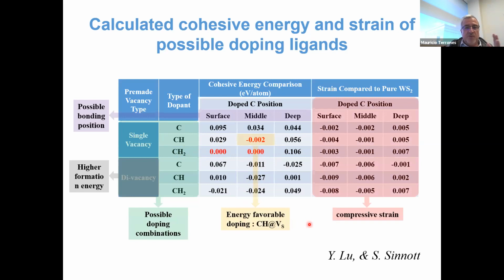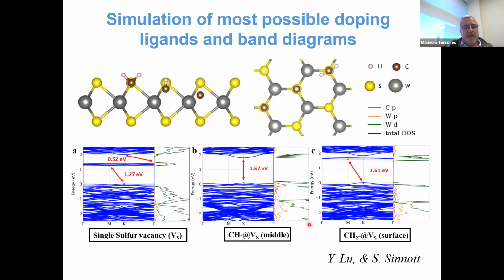So we have done some work on this. This is the carbon hydrogen, this is the carbon and two hydrogens, and this is just having the carbon on top, right? And this is the most stable one. You can see when you do this one, the band gap is reduced at the K point, and this is something that we could see in the experiment. If you remember, we could reduce the band gap by a factor, and this reduction can be explained here.